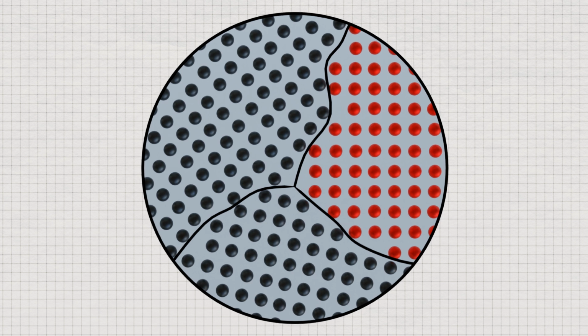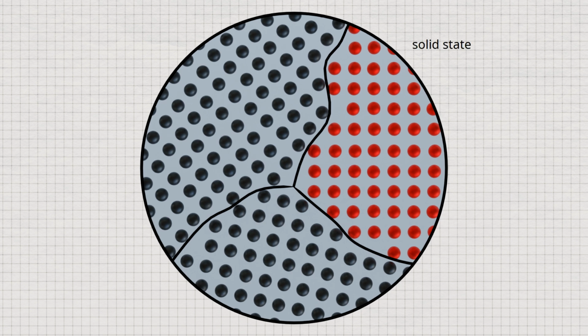If the atoms of the alloying elements can occupy neither regular lattice sites nor interstitial sites in the base lattice of the host material, the different atoms cannot be arranged in a common lattice structure. This is the case, for example, when the alloying element has a different lattice type or completely different chemical properties to the base material. During solidification, the atoms are displaced from each other's lattice.